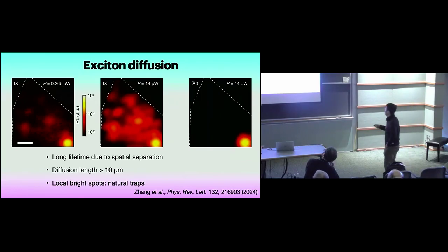So initially, we may say that now if you generate exciton, they like to escape, so maybe this is not good for condensate. But on the other hand, because they diffuse, they can cool down, right? So you inevitably create laser heating under your laser spot, but as they move away from your laser excitation, they can have more time to cool down and potentially get trapped in these natural traps to create a high density and cold excitons. So we think that this could be actually a good feature, and potentially we can look for exciton condensate in these cold traps.